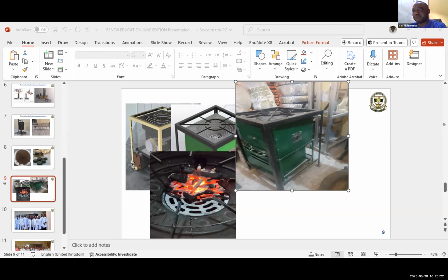And this hydrogel, in our focus, is for agricultural purposes, to release water as needed to the plants, particularly in drought-prone areas where the rainfall is very limited. So this is what we are doing at the moment. The process intensification of this particular technology is still on the way, and by the time we come to a conclusion, having optimized every parameter, the full details will be shared with the wider audience. At the moment, this is what we are doing in the Material Energy Laboratory, converting PET into PEG, and the PEG together with the crosslinker, which is basically the lignin, forms a hydrogel.